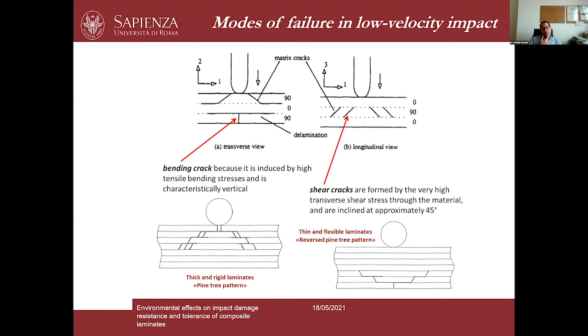And here you can see just a schematic view summarizing the typical damage that we can find in a composite material, where we have bending cracks, where we have shear cracks, and these cracks usually trigger the nucleation and development of extensive delaminations. Okay, the problem with these delaminations is that they can severely reduce the strength of a composite material, but at the same time, they can go easily undetected by visual inspection, because in many times, as you can see here, they are located inside the specimen.